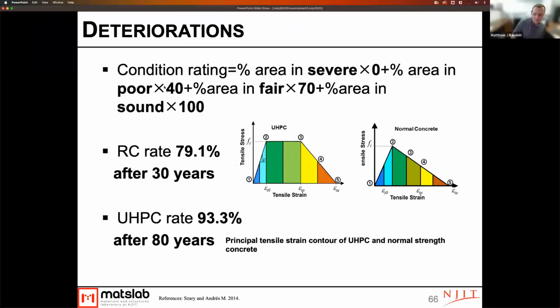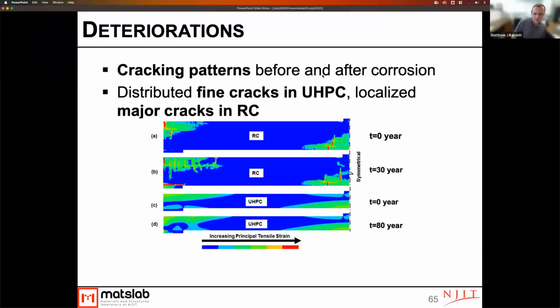Okay. So basically, what we did was, and I don't recall exactly what these particular values referred to, but what we looked at were basically principal tensile strains throughout a bridge area. So here, if we look at the section of bridge that we were looking at, you see these colors coincide with basically different levels of principal tensile strain. So red being a higher principal tensile strain, blue being the smallest principal tensile strain. And what we did is we counted up areas that were in different sections. So like blue and light blue, green and light green, yellow, red, et cetera.